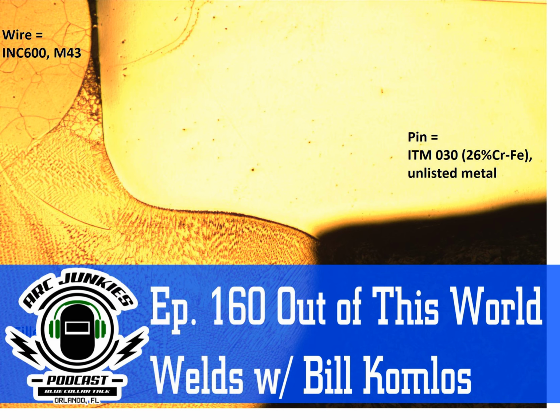So they're pushing, going back to they don't understand the voltage. They're pushing 23. I saw one guy put in 25 volts. I said, this can't even pass. And it's because they're still almost in the short circuiting range. They're not using 80% argon, which is a minimum you need to get a spray going. And that's only a recent thing that people knew in the last 20 years. I had people saying they were welding spray at 100% CO2. And you still see it in some of the sales literature, for crying out loud. I'm going, you boneheads.